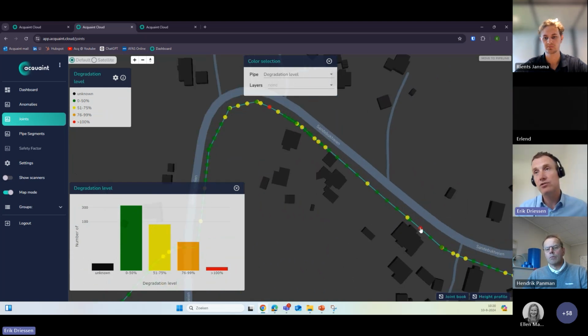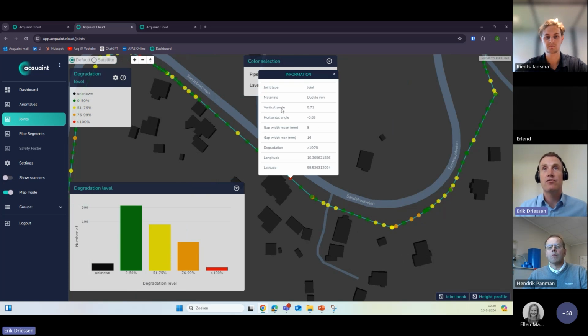So when I click on this joint, for example, you see that there's a vertical angle of 5.7 degrees, a small horizontal angle, but also a gap width. So it's clear that this joint doesn't sit nicely in the joint. So the pipe segments are a little bit shifted away and they're sitting under an angle in this joint.